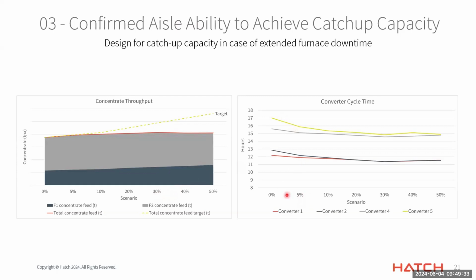So you'll notice the graphs reaching a plateau at around 30% increase in nominal feed rate. So even though the furnace has capacity to process higher feed rates, the converters downstream have optimized their cycle durations and hence do not have the same capacity to keep up with the furnaces. Hence, an additional converter would be required to meet throughput targets during the catch-up period.